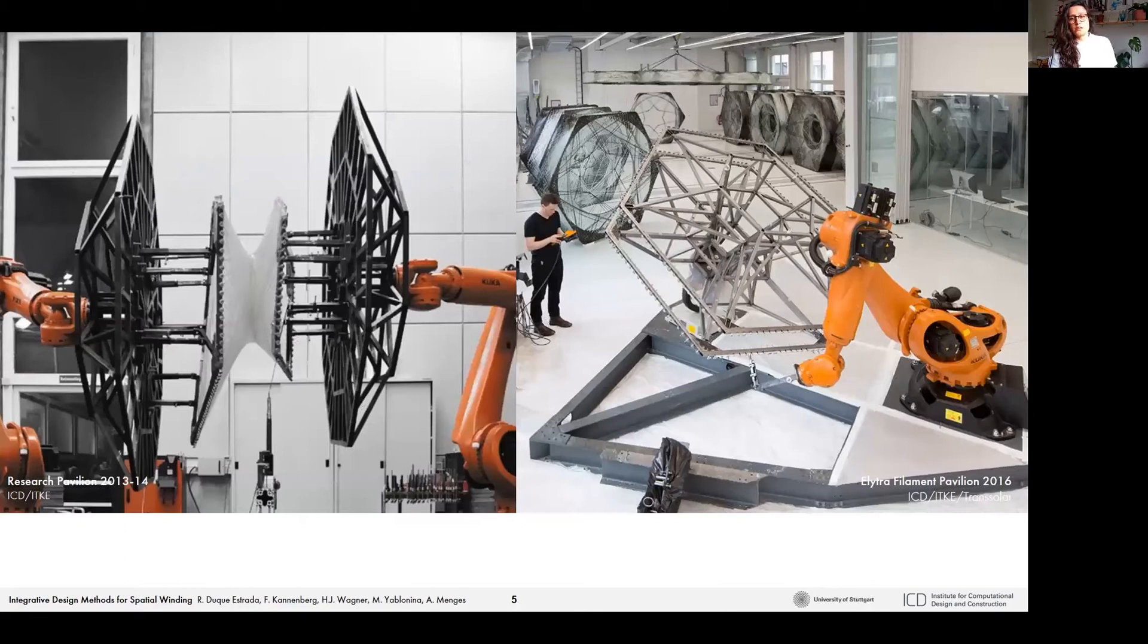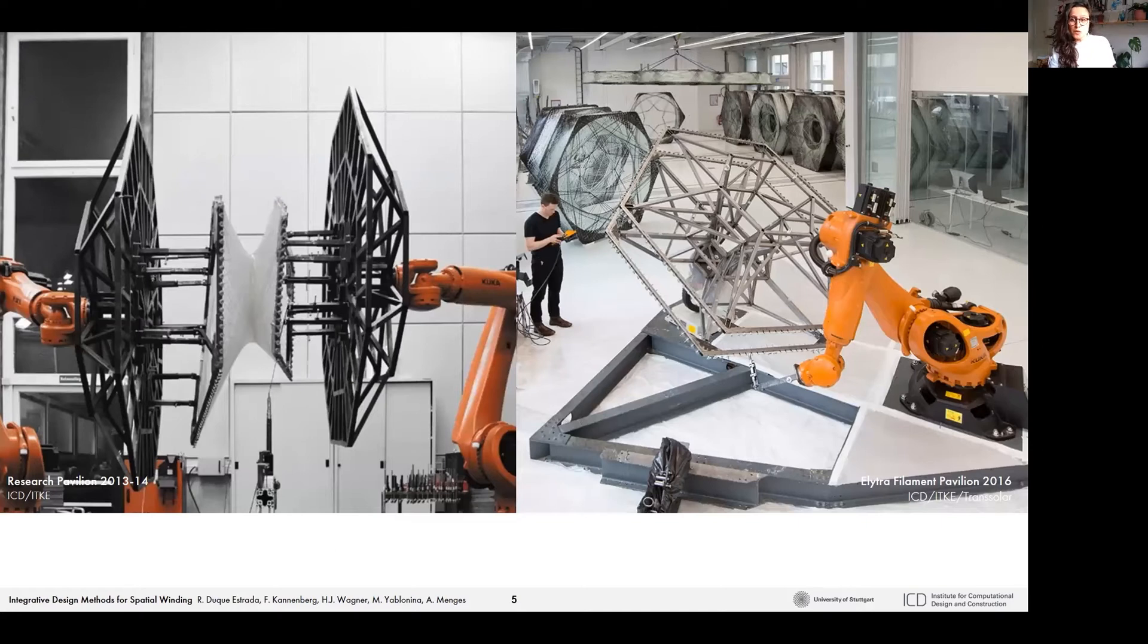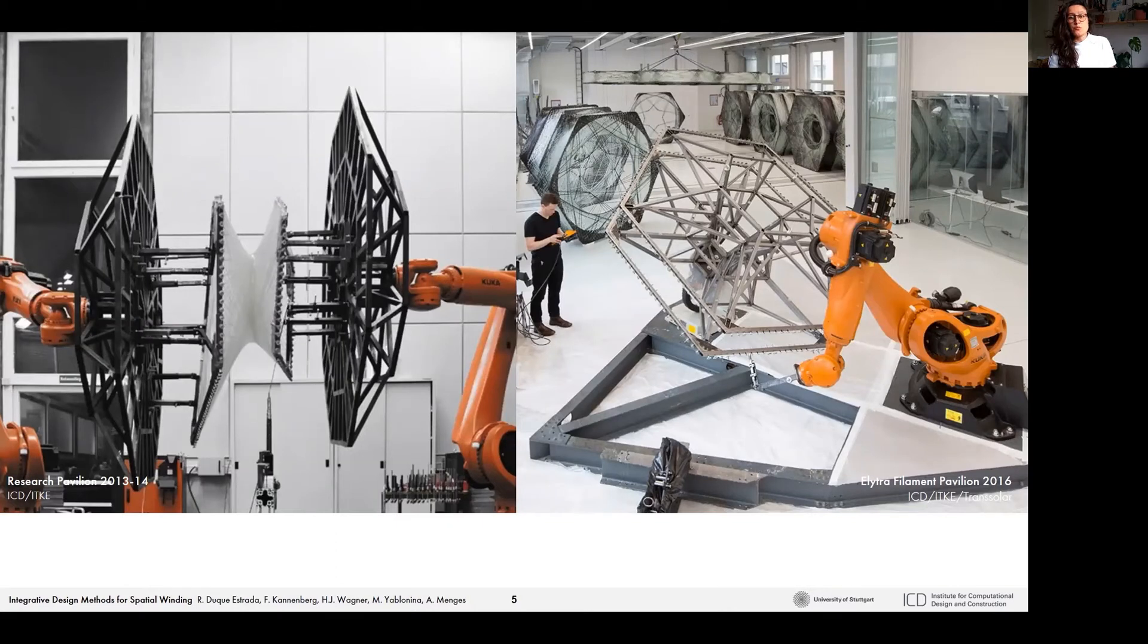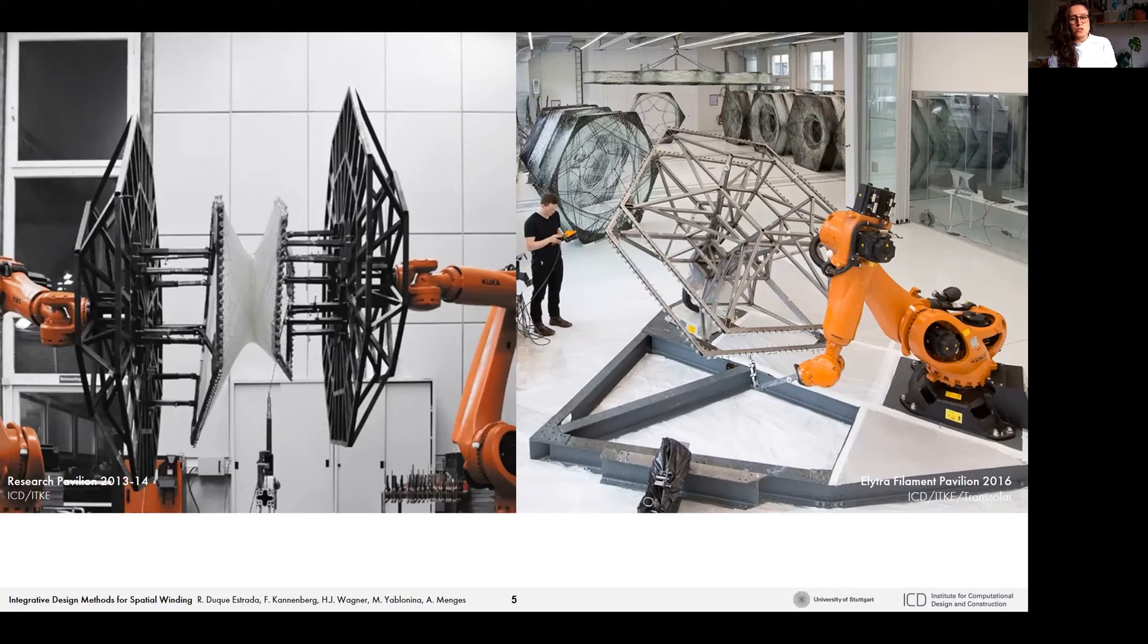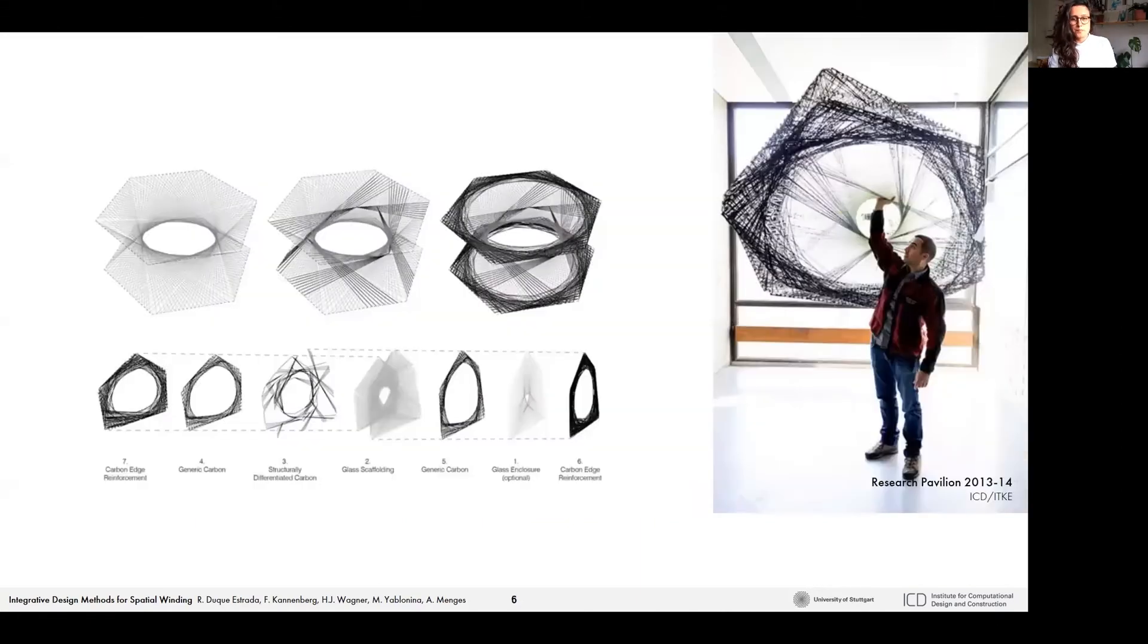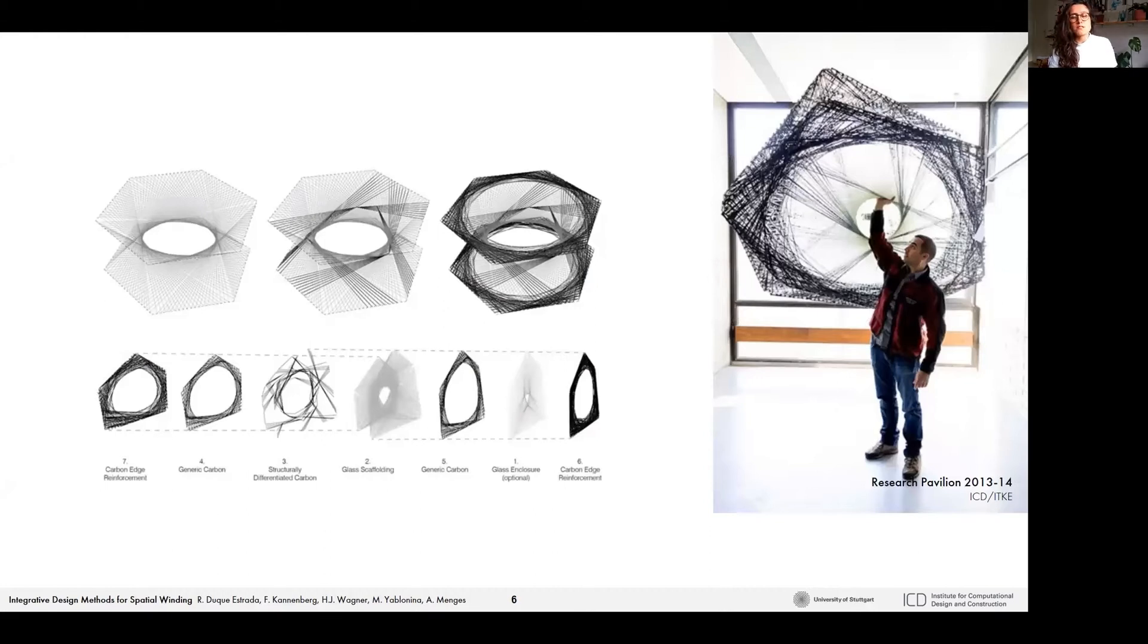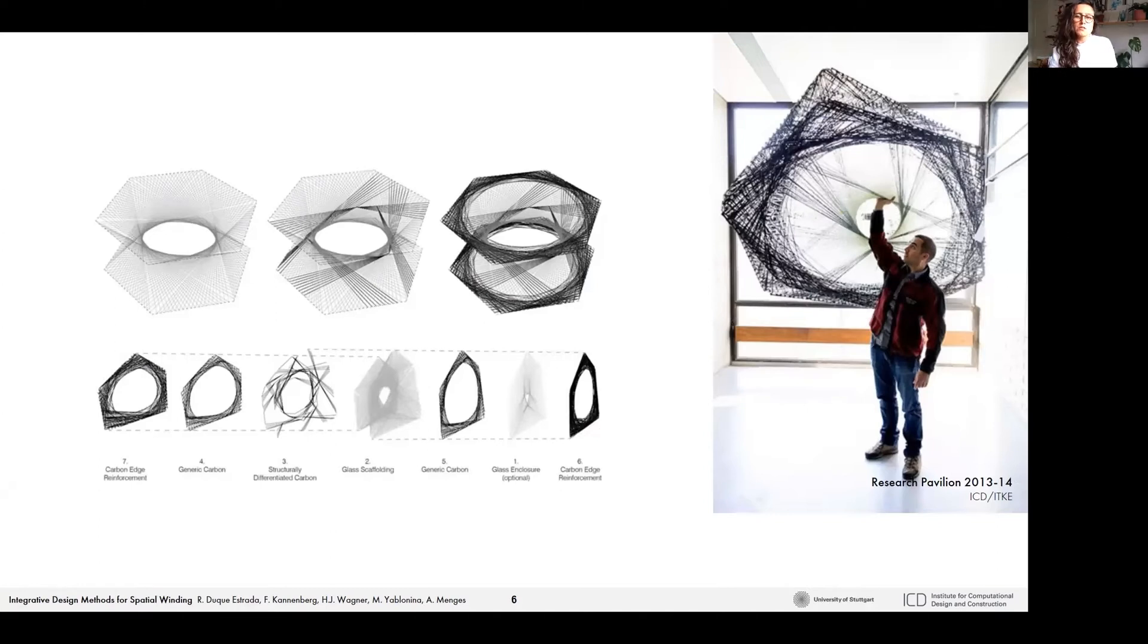The research conducted in this field relied on additive deposition of filament layers for fabrication of complex geometries with small formwork requirements. The majority of precedent projects deployed reconfigurable frames contrary to solid molds used in conventional industrial applications. These frames featured a large amount of preinstalled anchors for winding the filament around them. Strategic control of fiber tension and filament winding synthesis allows us to create complex double-curved surfaces that emerge from the interaction of multiple layers of filament pressing against each other.